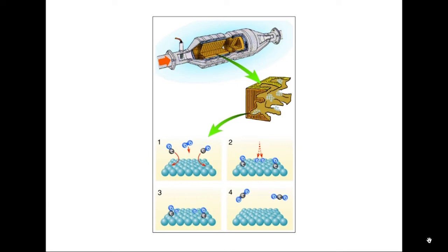It exposes planes of platinum group metals to the gases which have to be removed, in this case, carbon monoxide and oxygen. The oxygen molecules we have seen before are dissociating. They form chemisorbed atoms on the surface, and the CO molecules diffuse across the surface faster than the oxygen atoms. And when they meet each other, they can recombine and return into the gas phase as CO2. And in this way, a continuous flow of oxygen and CO will also form a continuous production of CO2, depending on the nature of the catalyst, the partial pressures, and the temperature. And this will usually always be the case, with some exceptions, and such an exception is shown here.